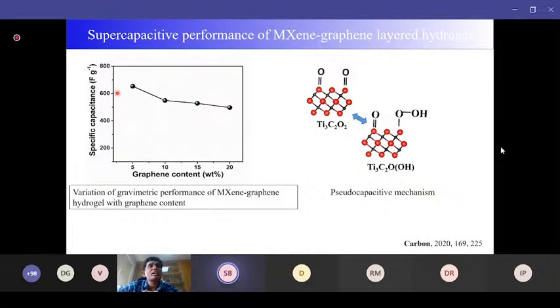And we got very good supercapacitive performance. More than 600 farad per gram, which was a record value for an MXene-based system, and the mechanism of its high capacitance is like this. This is the MXene. These are the functional groups, oxidative functional groups. So over here, in the sulfuric acid medium, this H+ ion can reversibly attach or detach, and as a result there will be a reversible change in the ionic state of those titaniums. So this is another Faradaic reaction, and due to this Faradaic reaction, it can give rise to good pseudocapacitance. And as a result of its high conductivity and high surface area, it also gives good electrical double layer type capacitance. In combination of these two, we are getting very good capacity.